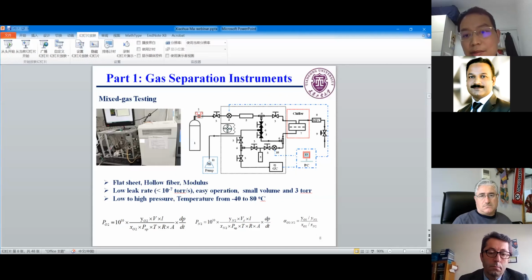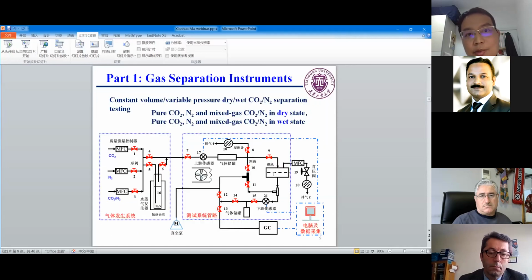As a result, we can get the mixed gas permeability for each gas in this case. And recently we made another instrument especially for CO2/N2, because the CO2/N2 mixtures, either from flue gas or from other conditions, are in a dry state. So I made this constant volume variable pressure dry and wet CO2/nitrogen separation testing instrument.